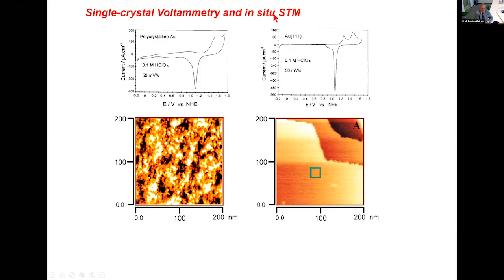About the studies of single crystal electrochemistry, polycrystalline electrode surfaces can be polished to mirror finish, and no one can see with the naked eye that they are not absolutely flat. But at 200 nanometer resolution, you can see it's a mountain landscape, and no one can see if there should be a molecule there or not. And the voltammograms, I'm not saying all voltammograms of polycrystalline electrodes look like this, but they are often not well resolved: the gold oxidation and the reduction of the gold oxide.